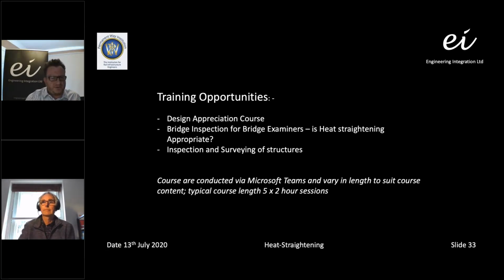Obviously, railway structures are significantly different in design, and we have undertaken a site survey at Limpley Stoke on a bridge that has been struck, and we've identified that we can't rectify the damage completely by heat straightening, because of certain elements of restraint and tears within the bottom flanges, etc. So we've recommended that some cutouts are required for that particular structure, and we can replace elements and straighten those elements, and then use heat straightening as a secondary activity.